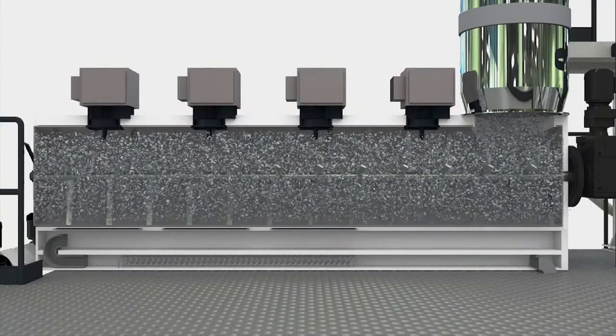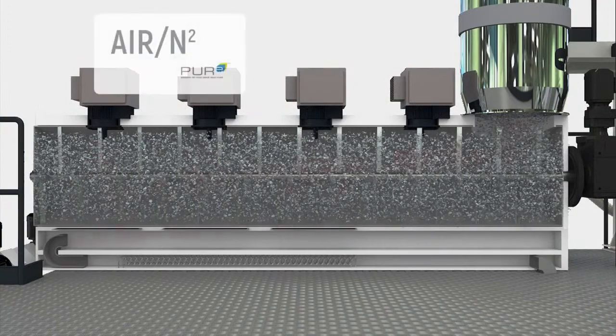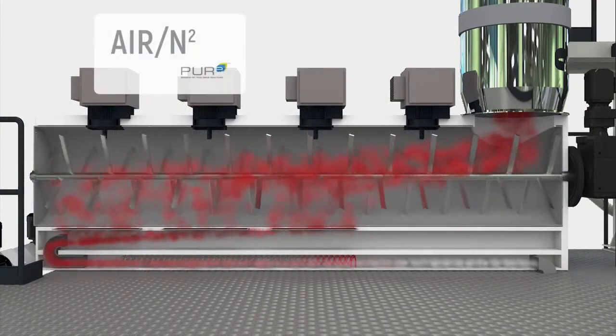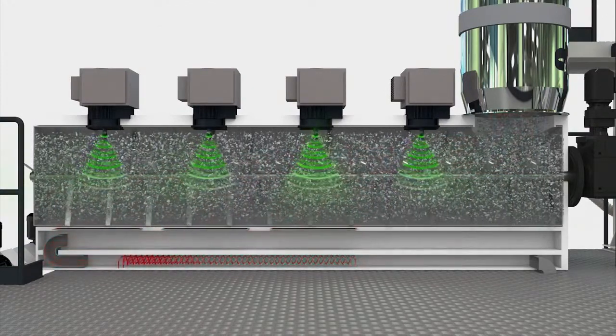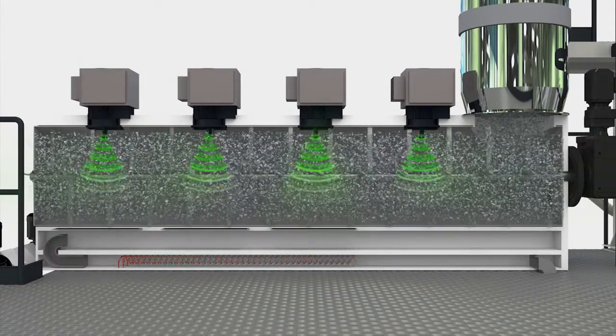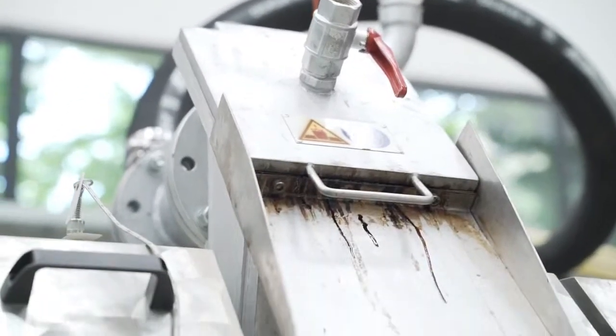The configuration of this continuous system can be in line with pelletizing or offline to process material independently. Bandera technology applies the combination of hot air and microwave treatment to speed up VOC drop compared to similar technology on the market. Selective microwave heating increases VOC diffusivity in the polymer while minimizing energy consumption. Materials such as polypropylene can be cleaned out in 2 to 4 hours, while HDPE, the most critical polymer for its lower permeability, can take 4-6 hours in total. By reducing process time on the complete pellet treatment, hot and cold, machine overall footprint and material changeover time are drastically reduced.